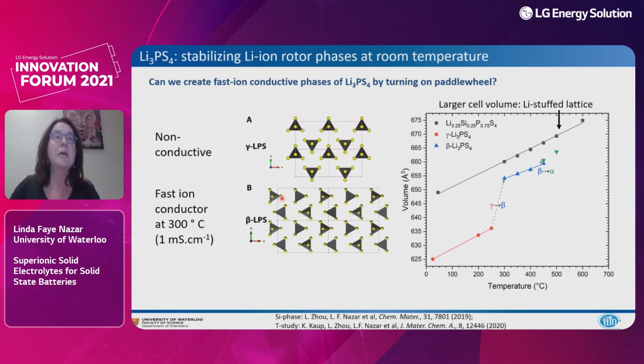And the polyhedral motif difference between the gamma and the beta is shown here. It's not really too important. What's more important is that as it undergoes the transition from the gamma to this beta phase, there is a large change in volume, an increase. And so we learned, this is a paper we published in Chem. Mater. in 2019, that one could actually create a lattice that's very similar to that of the beta phase by stuffing this material with lithium. What we really did was we substituted some silicon for the phosphorus. Silicon is +4 and phosphorus is +5. We effectively have to add lithium for charge balance. And so it's that additional lithium in the lattice that increases the unit cell volume even above that of the beta phase or an even higher temperature phase of the alpha. And this is one of the main factors in turning on the so-called paddle wheel effect.